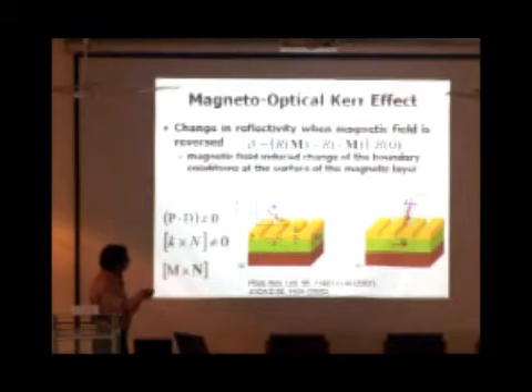So we match the grating structure to have the plasmon resonance match with the absorption in your magnetic layer. When you have both the plasmon excitation as well as the absorption in your magnetic layer, you can enhance the magneto-optical effect. In this case, looking at the Kerr effect, we are seeing three orders of magnitude enhancement in magneto-optical Kerr effect using this.